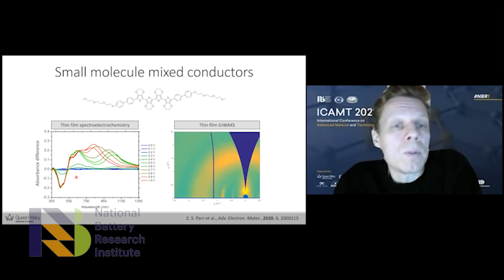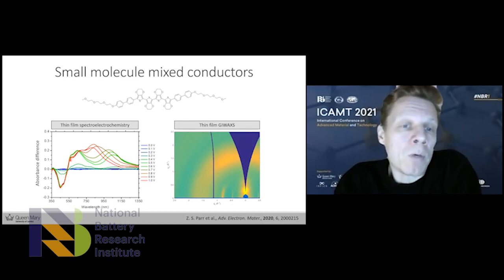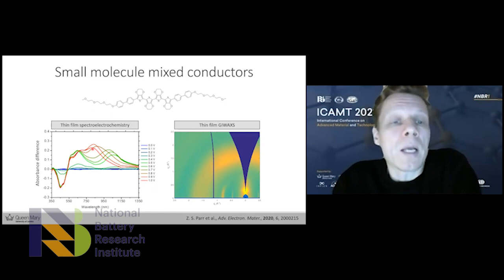When we do thin film spectroelectrochemistry, so we look at the optical properties as we apply a potential, we can see that we get a bleaching of the neutral state, and first we generate a polaron species, so a radical cation shown here in green, and when we increase the potential further, we get a dication, a bipolaronic species.